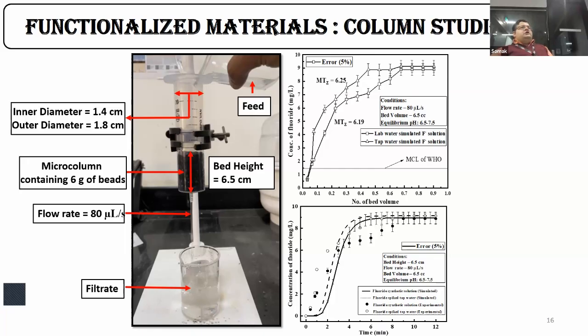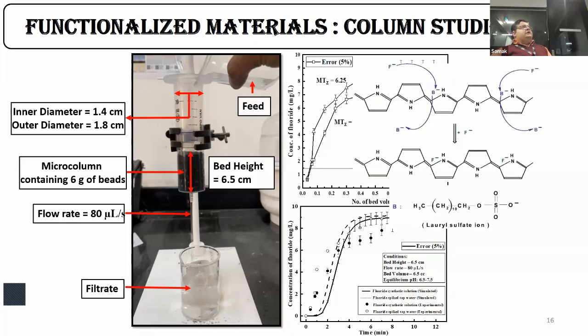We carried out a COMSOL-based analysis, and we can see from the lower graph that the one for the synthetic solution nearly matches. In the case of the tap water solution, there is a slight deviation because of the presence of different coexisting ions, which causes hindrance to the fluoride solution effect, but towards the end of our experiment, it also starts mimicking the experimental studies we have done.